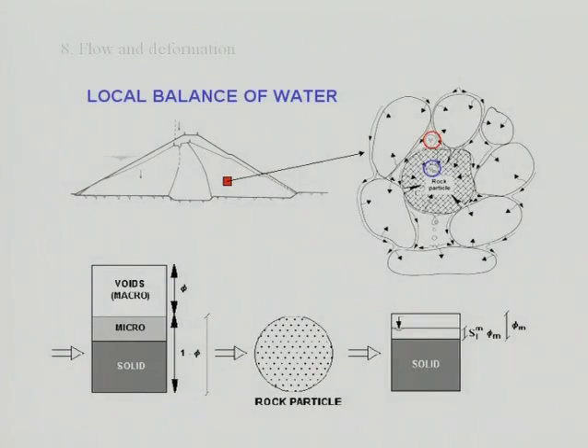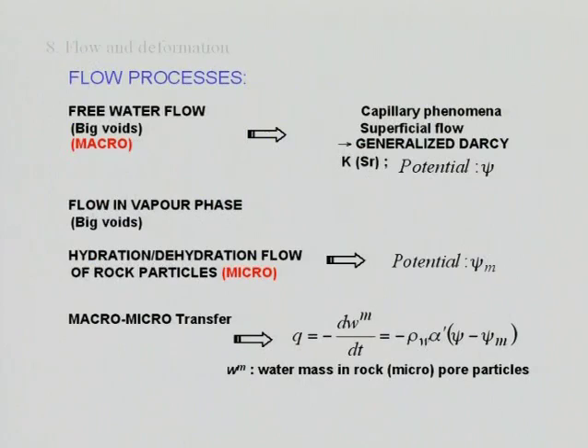So this is, in a phase diagram, very simply, what I mean. We have the macro voids and the micro voids. The micro voids correspond to the actual rock particles. And the micro voids can actually be unsaturated, we have seen the water retention curve for the microvoids, and then we may define even a porosity, certainly for the microvoids, and also a degree of saturation for the microvoids. And then we may speculate a little bit on what the flow processes are.